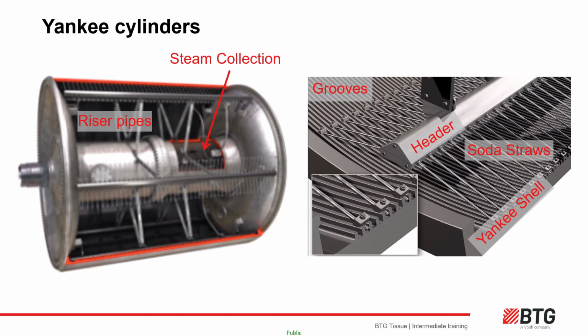Keeping the Yankee internals clean and free from corrosion, deposits or scale is also vitally important, not only from a safety aspect of a pressurised vessel, but any blockages in only a few straws can lead to cold spots on the Yankee, giving non-uniform CD and MD drying. This can lead to issues with Yankee surface health and uniform shape and topography issues.